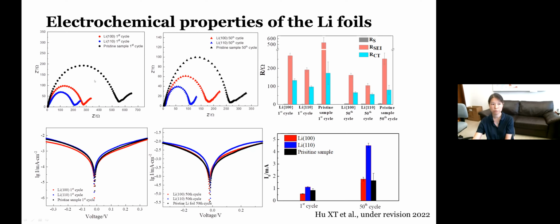As you move from the first cycle to the 50 cycles, you see a decrease in both SEI resistance and the charge transfer resistance for all samples alike. But among all of them, the lithium-110 is always associated with the lowest SEI resistance and the charge transfer resistance.